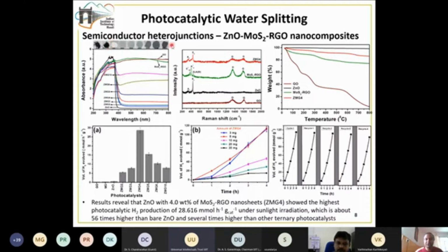Then another very important property is the thermal stability of the material. How long is this material thermally stable? We studied it using TGA, thermogravimetric analysis, and we found that the samples are stable up to a good temperature. And then after doing these detailed characterization studies, we subjected this material to photocatalytic hydrogen evolution. We used direct sunlight, and we used water as a solvent along with certain scavengers, because the hole scavengers will scavenge the holes, and then the electrons are directly involved in this process.